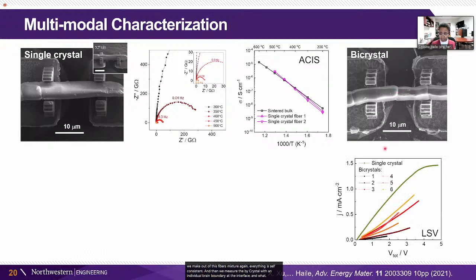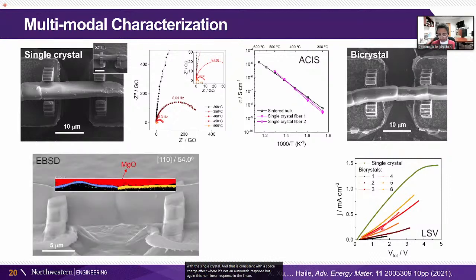And what we see in our DC measurement is that there's a huge impact of having this interface. This is the measurement of that single crystal, this one right here, and then 6 bicrystal samples where you can see that the current is much lower, and it's also now nonlinear compared to what it was with the single crystal. And that is consistent with a space charge effect where it's not an ohmic response, but again, this nonlinear response in the linear sweep voltammetry.